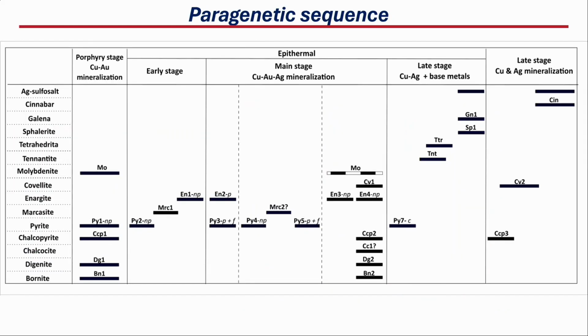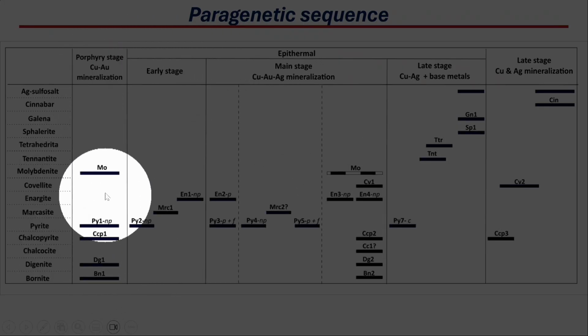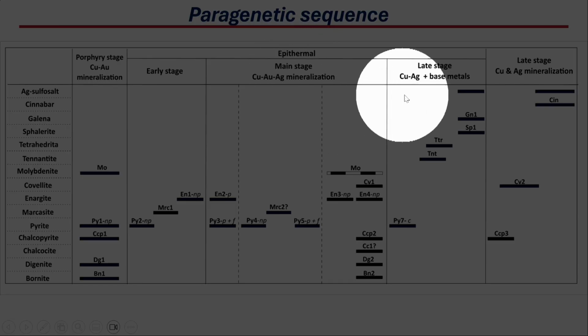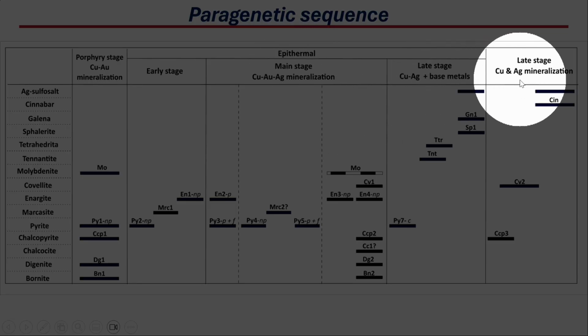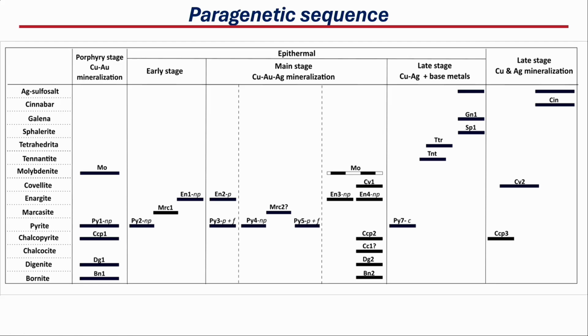And so I won't go too much into detail on this. This is a really long paragenetic sequence trying to summarize the deposit. But overall, we can see that we have a porphyry stage copper-gold mineralization, and we have the epithermal itself, and we have a possible late stage which is associated with the supergene environment. So here I will focus on the epithermal and in particular on the main stage. So we have an early stage, a main stage of copper, gold, and silver mineralization, and a final late stage with copper and silver. So we see here that we actually can find different cyclicity starting from the non-porous pyrite in